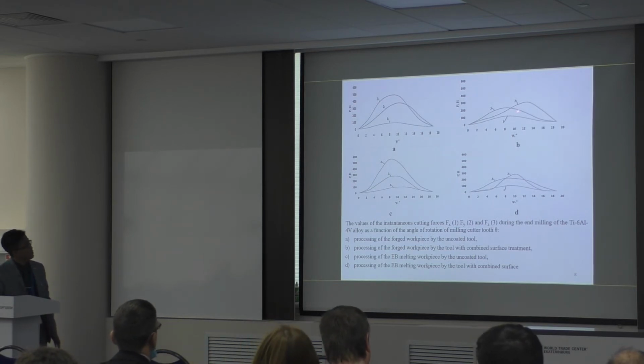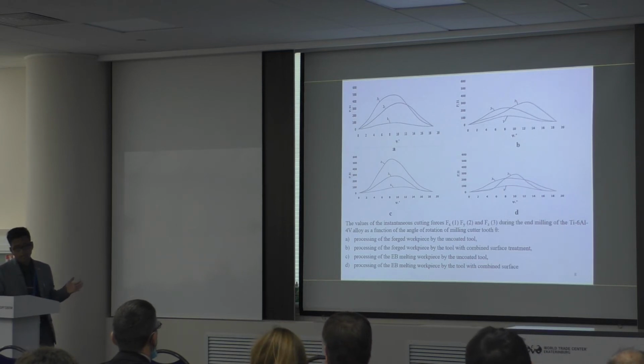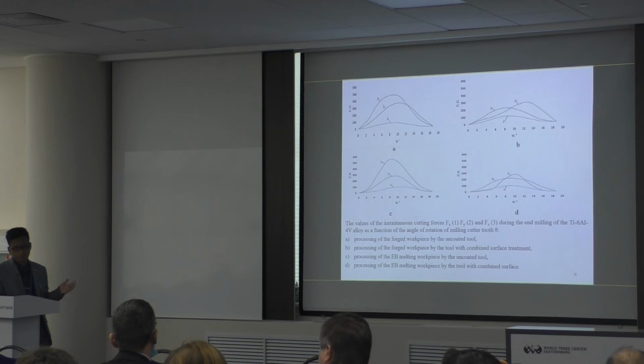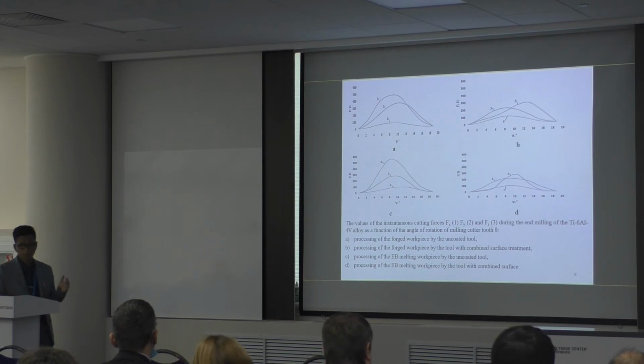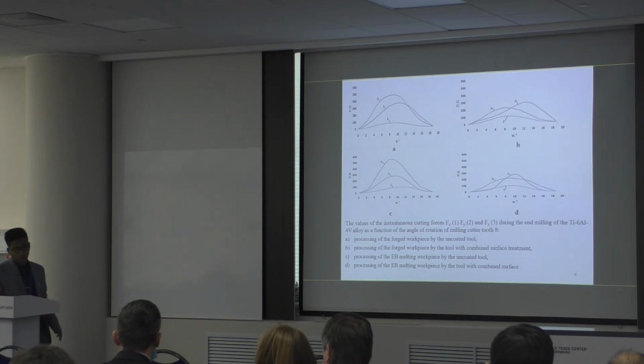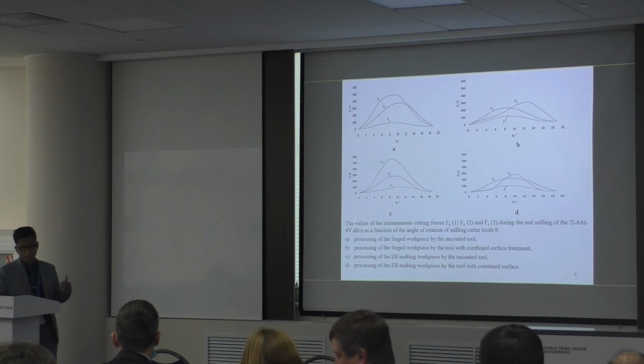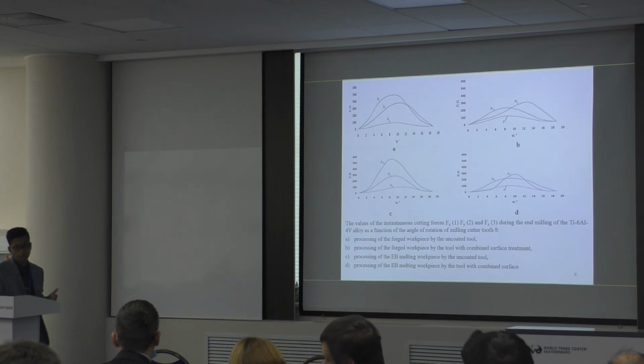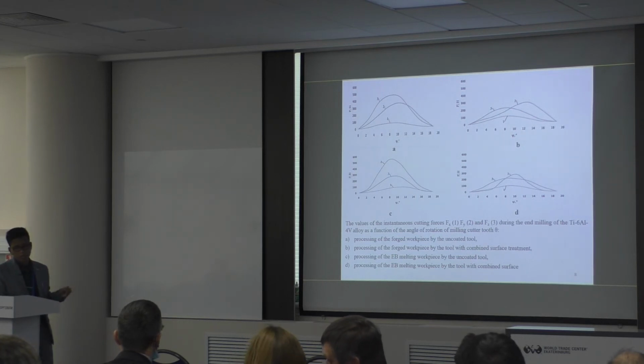Figures A and B, milling using a tool with a hardened layer by means of complex surface treatment. The cutting force Fz is reduced by half when processing a forged workpiece. Figures C and D, 2.5 times when milling an alloy obtained by electron beam method. The value of Fy force decreases slightly in this case. Figures B and D, when processing a workpiece obtained by electron beam method, the components of the cutting force are approximately the same.